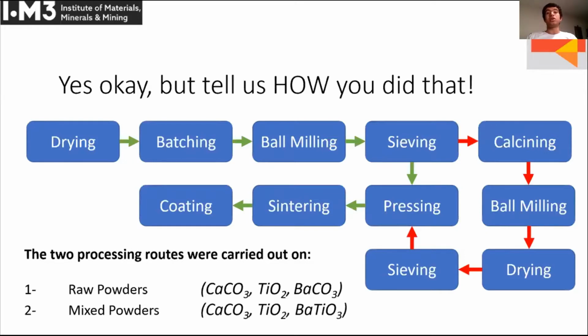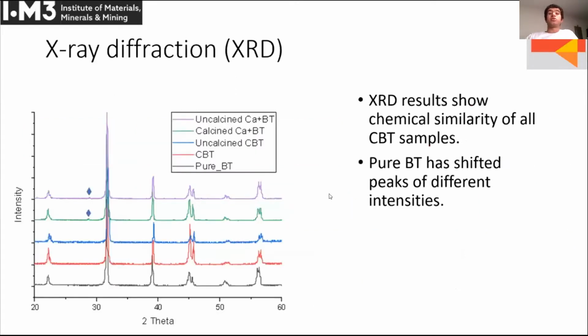So we did XRD experiments, and the scans essentially show that they're equivalent. Pure barium titanate, obviously you'd expect different peaks, so there's some shift if you can see it, and beyond 60 there's other shifts as well. But what I really want to show with this slide is that they're essentially equivalent, and we are in theory testing the same material.